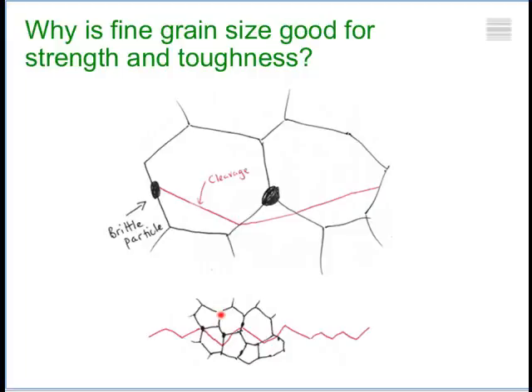So I want to stop there for the break. What I want you to think about is thermomechanical processing is an incredibly successful process, which no one in ordinary life is concerned about, because we make such incredibly good steels that they do not fail. How far can we go in refining the grain size using thermomechanical processing? At the moment, the steel industry can happily deliver to you ferrite grain size between 10 and 20 micrometers. Can we go down to 1 micrometer? Can we go down to 0.1 micrometer? And will that signal the next revolution in strength and toughness? So I will stop now for the coffee break for 15 minutes. We are exactly on time.